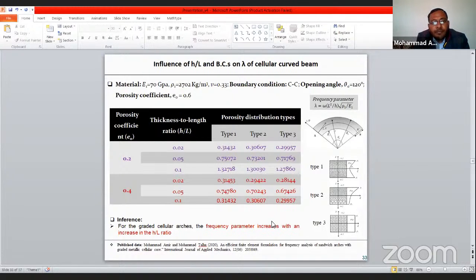Here we observe the influence of the h by l ratio, that is the thickness to length ratio, and the boundary conditions on the frequency parameter of the graded cellular curved beam. Here we consider the porosity coefficient E naught equal to 0.6, and the material properties are as taken earlier. The boundary condition is clamped, and the opening angle is 120 degrees. Here I have considered three different types of porosity distributions: type 1, type 2, and type 3. The results are presented for various porosity coefficients like 0.2 and 0.4, and thickness to length ratios of 0.02, 0.05, and 0.1.